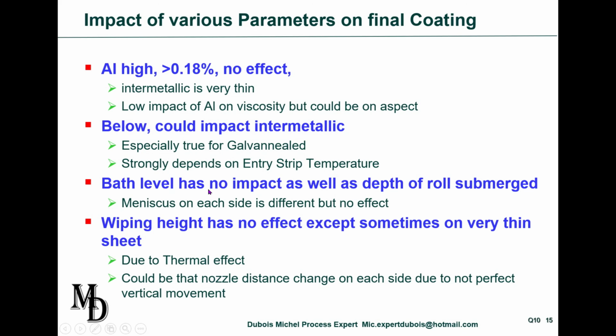On the opposite, bath level, from my research, has never been shown to impact the final coating weight, nor has the location of the final stabilizer roll in the pot. Wiping height also has no effect, except sometimes on very thin sheets, because you could have a thermal effect. If you are wiping too far away from the pot, strip cooling on its path from the pot to the nozzles will of course be higher because of time. And in the case of very thin sheets, like 0.2 to 0.3 millimeter, this could decrease the strip temperature. It means increasing zinc viscosity, and it will impact that.